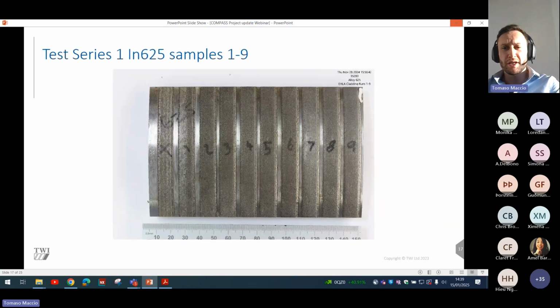Some of the initial trials that we completed, you can see the surface roughness. So this is samples 1 to 9 of the 28 that we completed. You can see that there's a good level of surface finish for the Inconel 625 samples that were printed here.